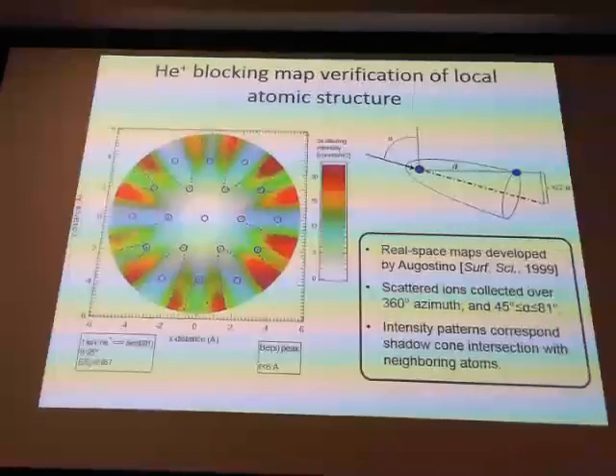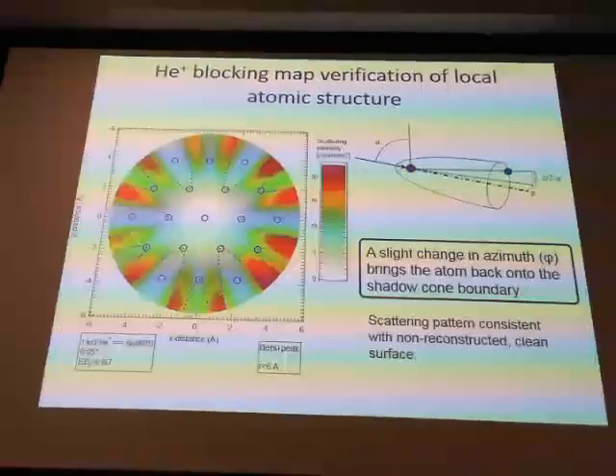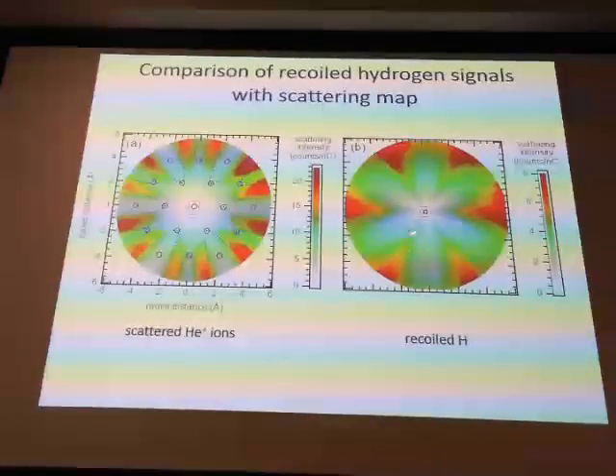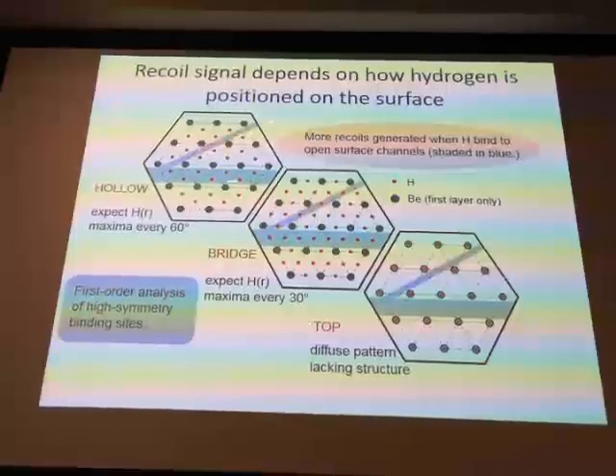And we were able to get good atomic crystallographic information about the substrate itself, but then also we were able to determine the binding site of the hydrogen on the surface. So this signal here is the signal that arises from the hydrogen binding, chemisorbed to the surface. And it's really as a result of ion channeling along different open lattice directions on the surface. So depending on if the hydrogen is sitting in hollow sites or bridge sites or on top sites, the beryllium atoms here, these green atoms, and then the red dots are the hydrogen here.